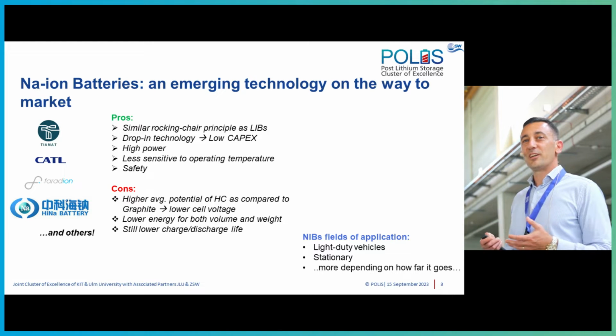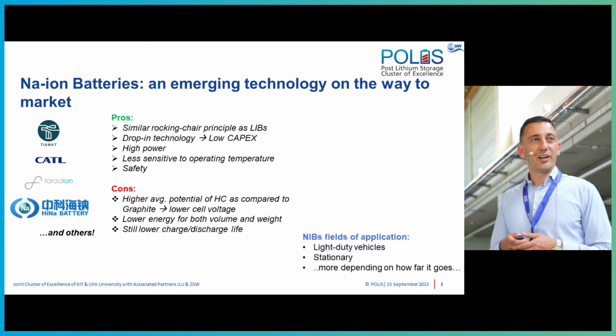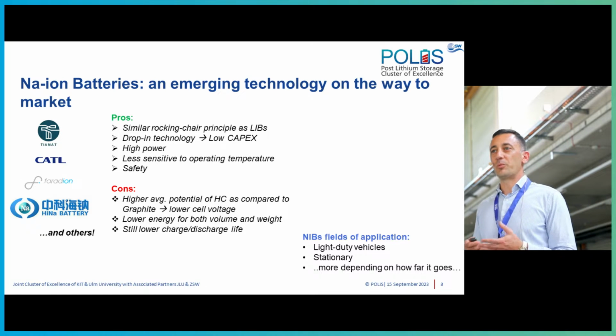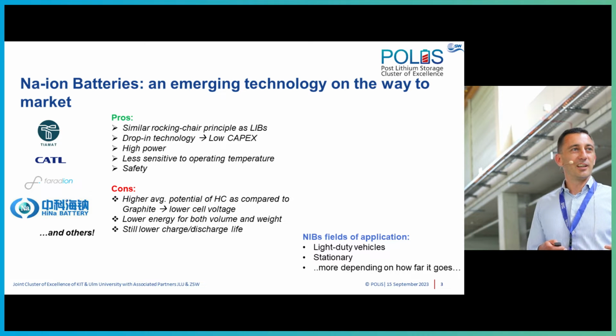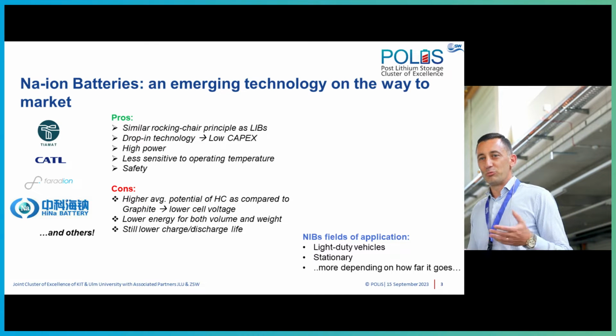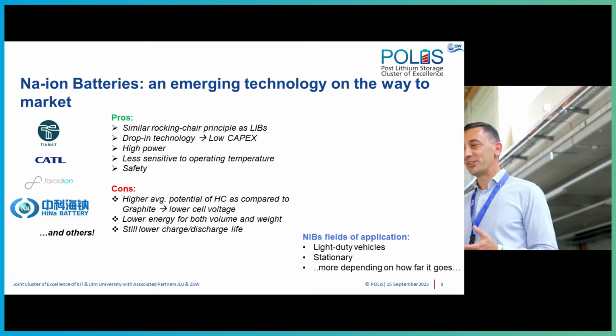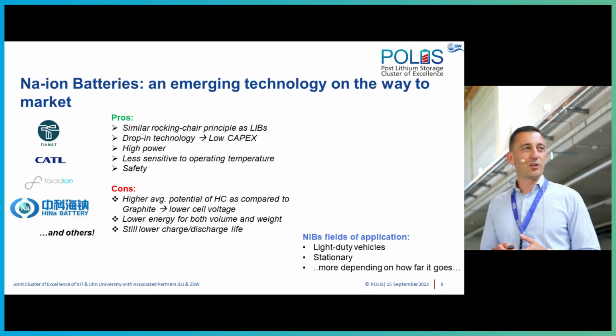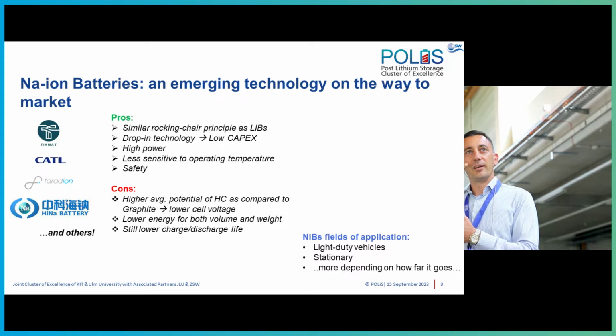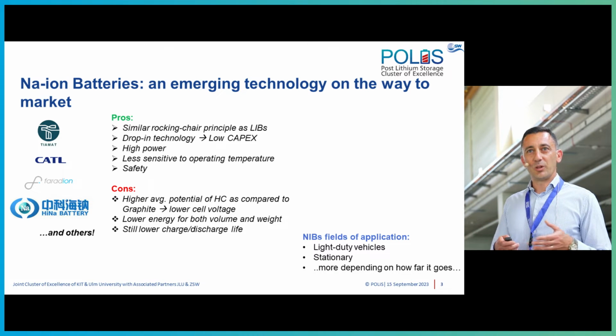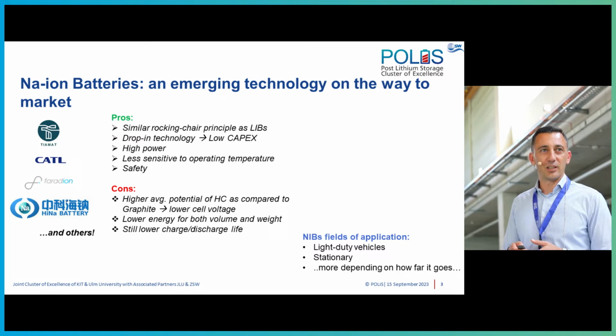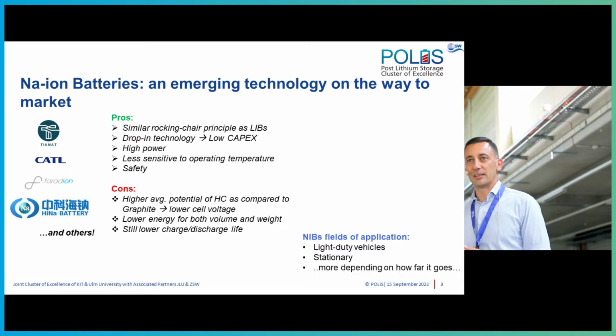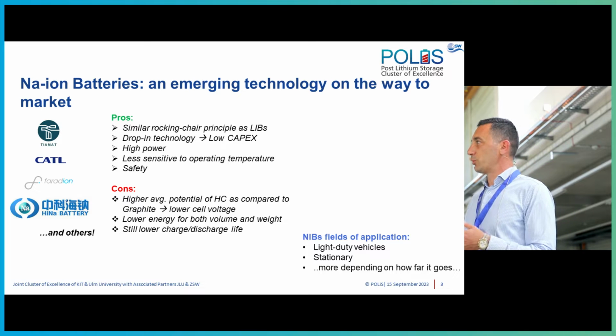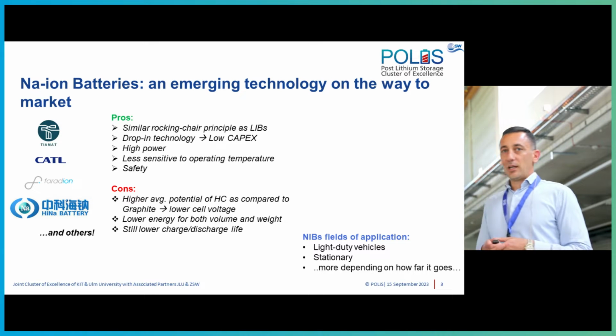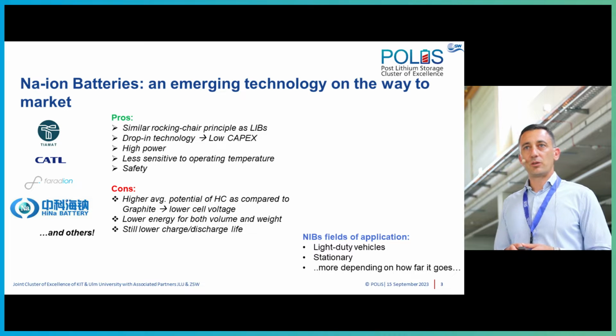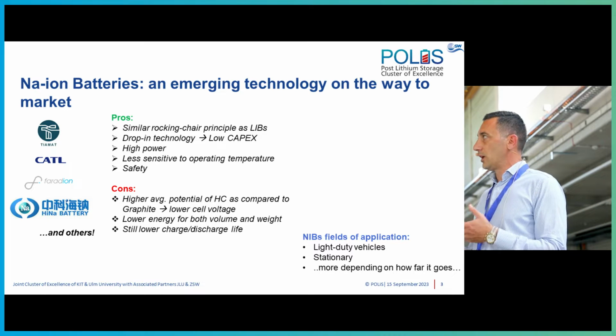This doesn't mean that our job is actually done. If you compare to what happened to lithium-ion batteries, the first one was commercialized in 1991 by Sony. Relatively poor specific energy, about 90 watt-hours per kilogram. And now, after 30 years, we are almost hitting 300 watt-hours per kilogram on the best, most performant cells.